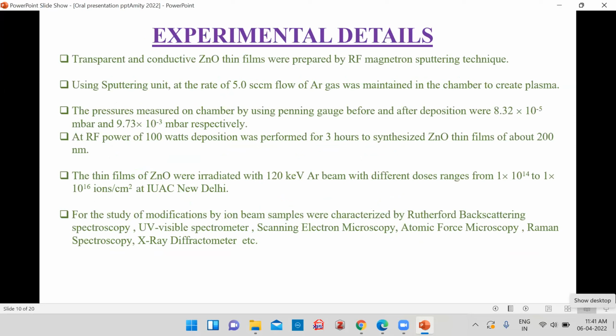These are the experimental details of my work. We have deposited the thin films of ZnO by the RF sputtering technique, where a 5.0 sccm flow of argon gas is maintained in the chamber to create the plasma. The pressure before and after deposition is 8.32 into 10 to the power minus 5 and 9.73 into 10 to the power minus 3 respectively. RF power of about 100 watt is used when deposition is performed.